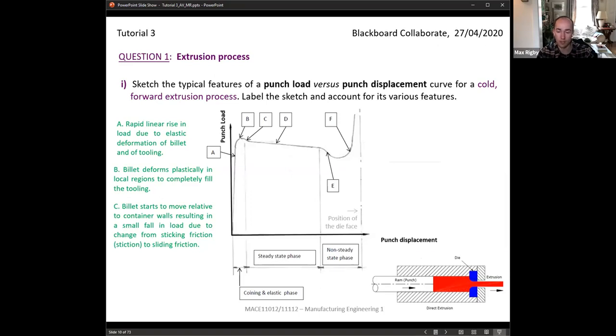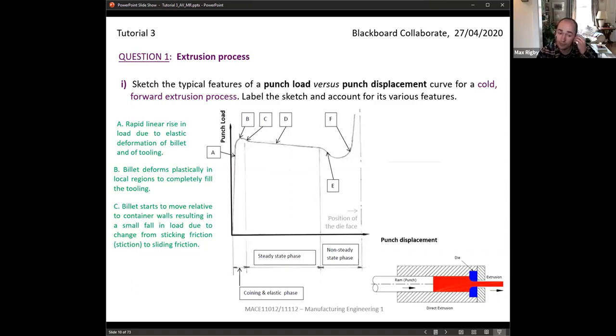At part E, the ram is getting close to the die and the amount of material is getting much lower. The material enters the region where plastic flow is dominating — this is the part flowing through the die. At this point the load decreases more quickly due to plastic flow, and the sliding friction from the main billet against the housing is almost completely gone.